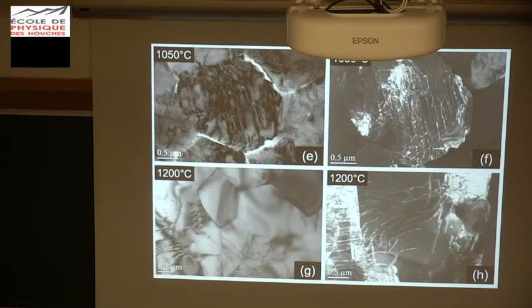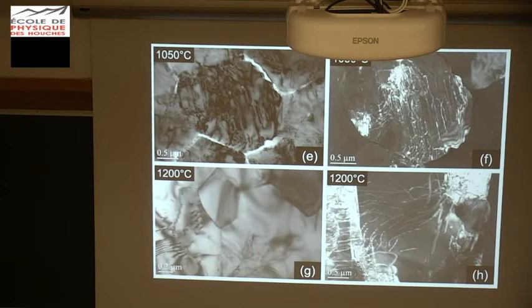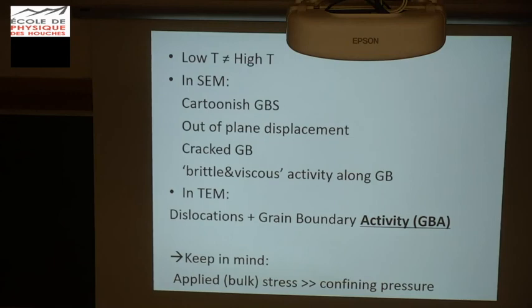You have those steps or teeth or whatever — we haven't yet proven that they were crystallographically controlled. We're suspicious about that, but what we have now is not that clear. And at 1200°C, no gaps, no teeth, no asperities, no cracked grain boundaries. We go back to a very classical geologically relevant picture for the convecting part of the Earth — tight grain boundaries and dislocations.